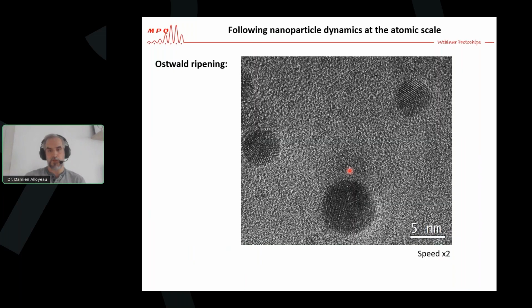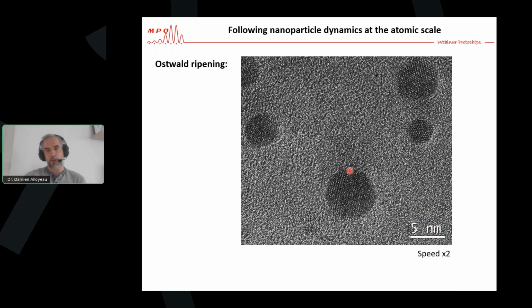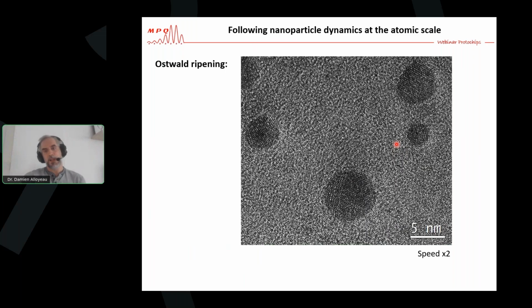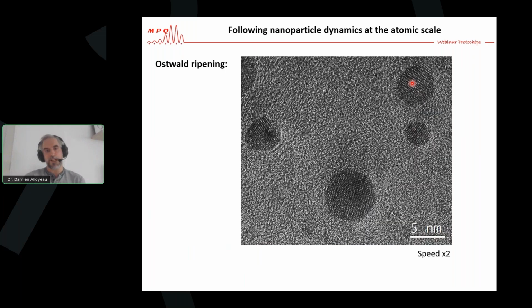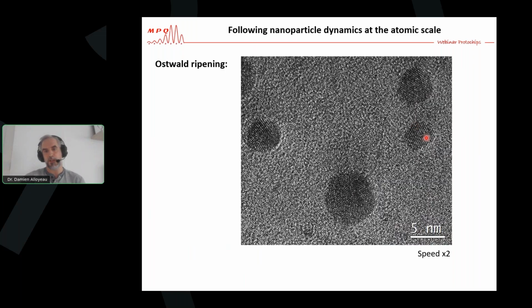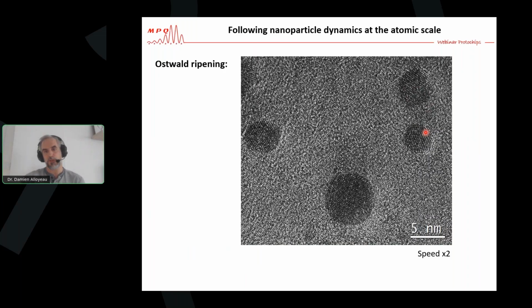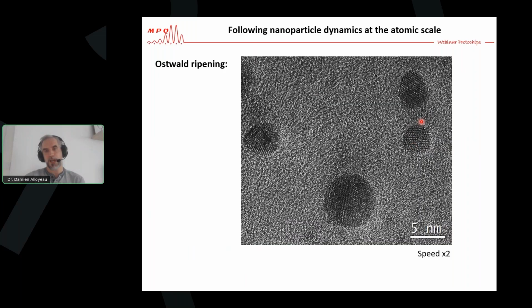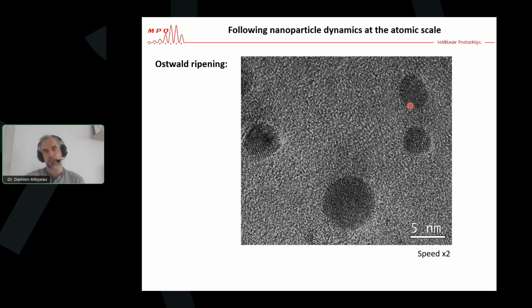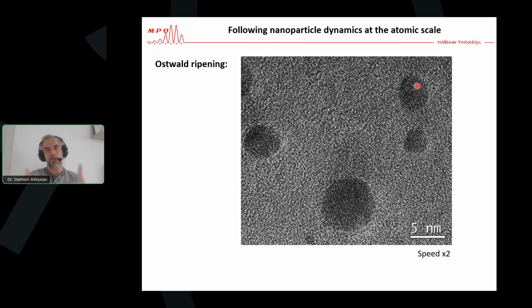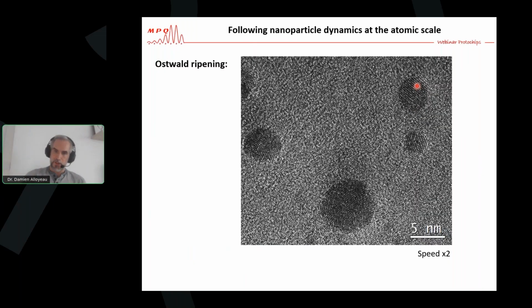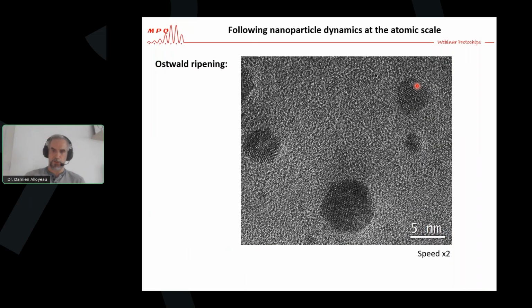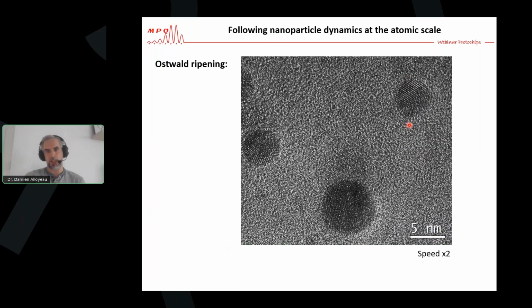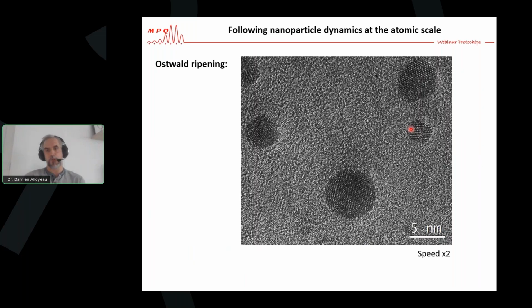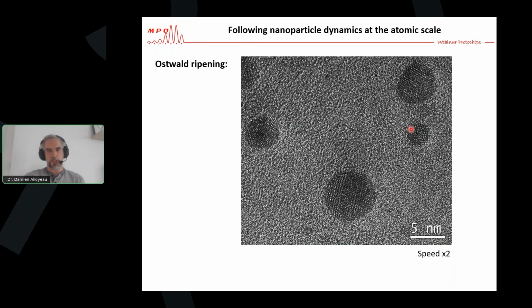In fact, something that we have to realize when we talk about Ostwald ripening is the fact that nanostructures constantly exchange atoms with each other. You see here between those two nanostructures, this one is increasing in size, while this one is reducing. So you have an opposite, an anti-phase growth and etching mechanism between those two nanostructures, because they are exchanging atoms. At some point, these small nanoparticles disappear because they are completely dissolved.